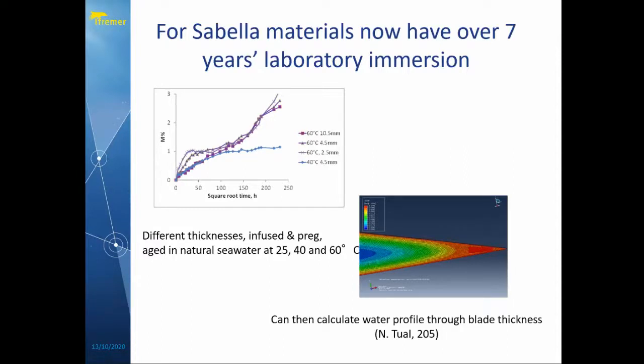And so from these kind of curves, we can get information on the diffusion coefficients, and these allow us to then calculate the water profiles through a blade thickness. This is an example from PhD work by Nicolas Tual, where we can then get a water profile. And once we've got a water profile in the structure, we can start to look at what the water is doing, relating the water presence to degradation mechanisms, and we have a basis for constructing a lifetime prediction model. Next, please.